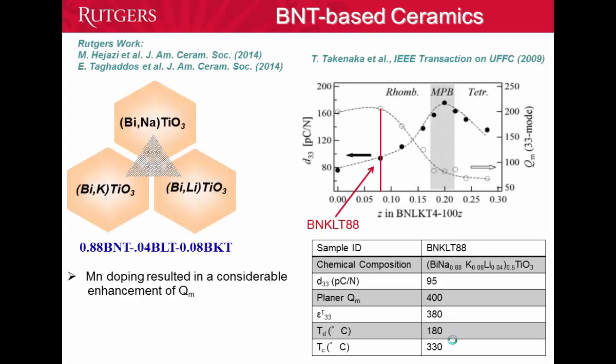As an explanation, the solid solution of bismuth sodium titanate, bismuth potassium titanate, and bismuth lithium titanate has been chosen to work with. You can see the properties of these compositions, which have been taken from Professor Takenaka's work in 2009. These solid solutions can make a rhombohedral, morphotropic phase boundary, or tetragonal structure.